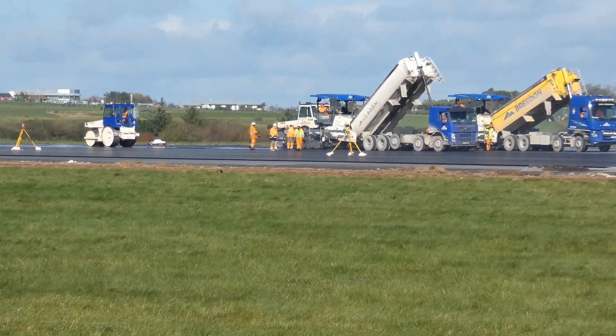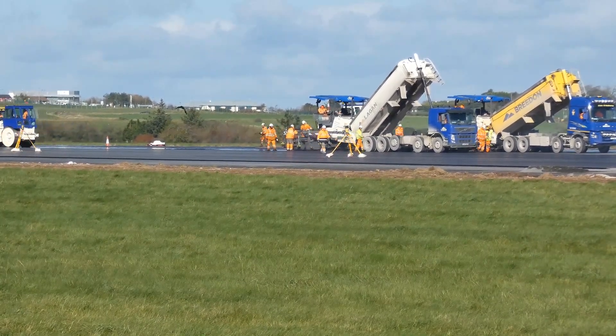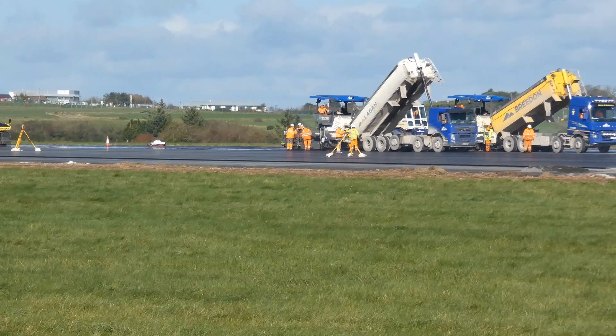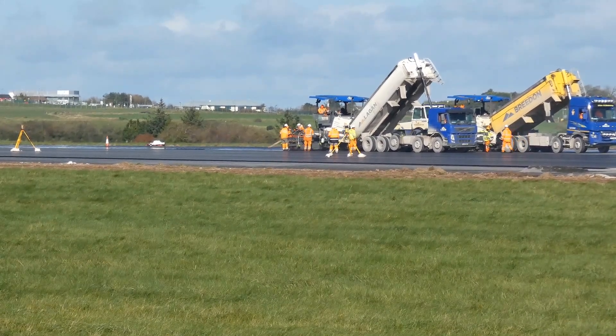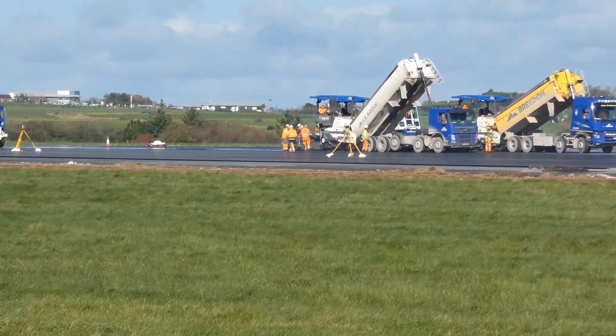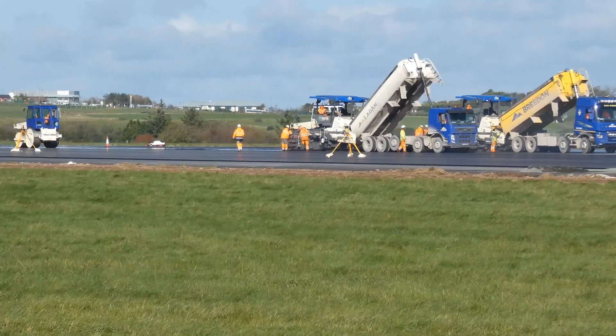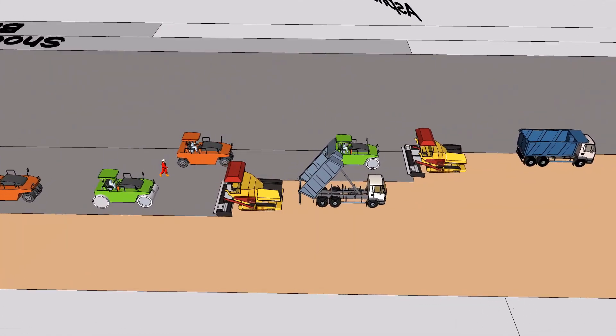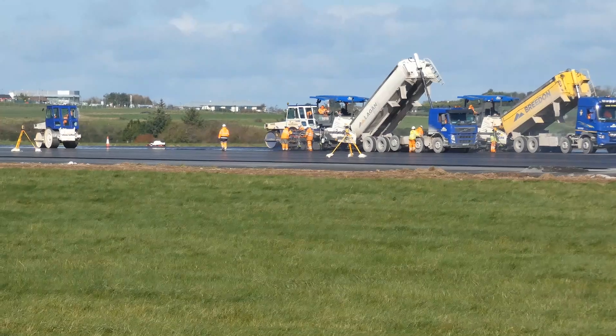For laydown of the hot asphalt mix, the surface is cleaned using lorry sweepers, which consist of several storage tanks and side and front roller brushes. A lorry bitumen tank with spray bar is used to apply hot tack bitumen coats to bond the pavement layers. Paver machines on tracks lay down the asphalt hot mix, with a maximum pave width of 8 meters. Echelon paving uses two or more pavers in a staggered formation to eliminate cold longitudinal joints that tend to ravel and leave gaps. Joints between layers are staggered by 150 to 300 millimeters, as joints are a weakness.